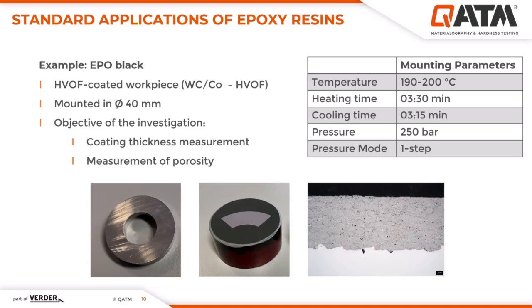Precise sample preparation is especially important to avoid chipping of the coating and to measure the porosity accurately. The relevant sample segment was mounted with the epoxy resin using a hot mounting press with a hot mounting time of in total 7 minutes. Preparation then followed the DVS standard using only grinding steps with diamond grinding wheels up to a grit size of 3 micrometer.